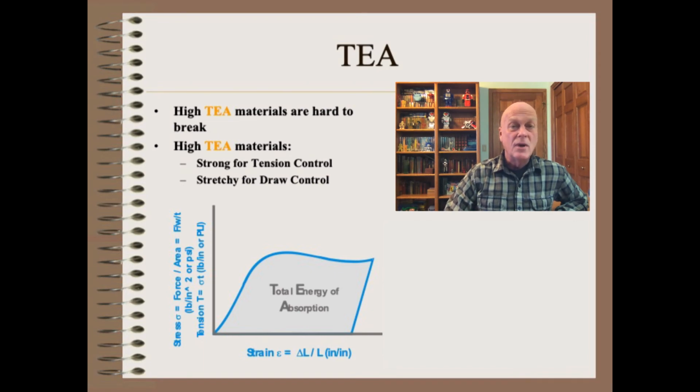Let me close with one last concept I hinted at earlier. That is, which lab test you use matters. It matters a lot. This is above and beyond the sample size and variation issues we already discussed. Recall in the previous slide, we showed that Mode 3 tear measurements are quite different than Mode 1 web breaks in your machine. Thus, none of the researchers have found a connection between tear and runnability, at least so far.